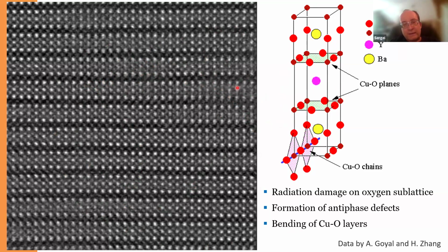In some places, the sublattices corresponding to the second type of atom, these layers, actually become disordered. So what's going on? This material was irradiated, and the radiation introduced weak damage on some of the sublattices. So we can see the strong atoms, but not the weak atoms.